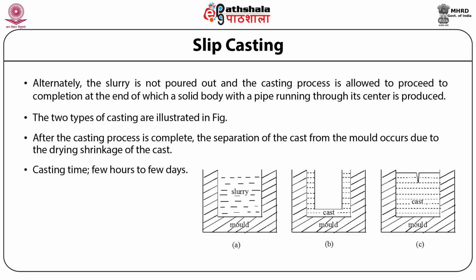The casting time may range from 1 hour for a porcelain part with a thin wall to several weeks for a refractory cast of thickness 30 centimeters. The casting time may be reduced by pressure casting or vacuum casting.